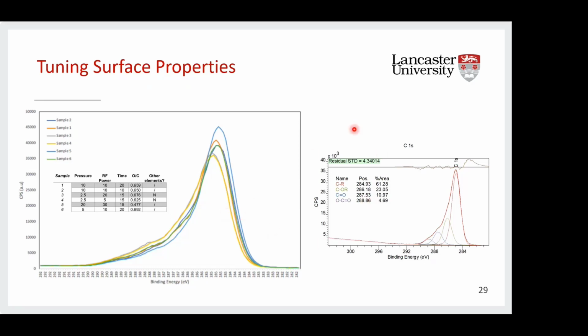If we look at this individual spectra here, you have 3 key carbon bonds that we want to keep an eye on. So you have the hydrocarbon peak that sits around 285 electron volts. You then have the CO bond at approximately 286 electron volts, and then the C double bond O at 287.5 electron volts. And you can see here that as you're shifting those plasma parameters, those bond peaks are shifting.